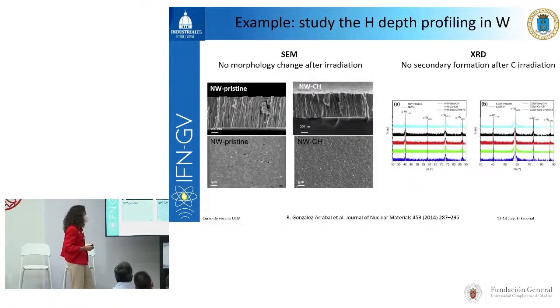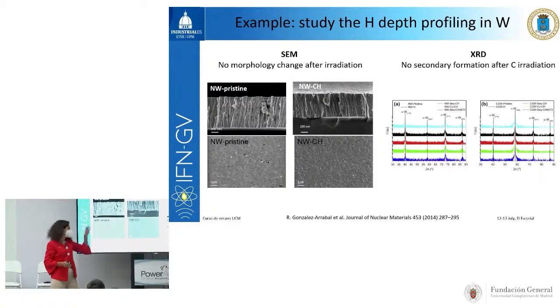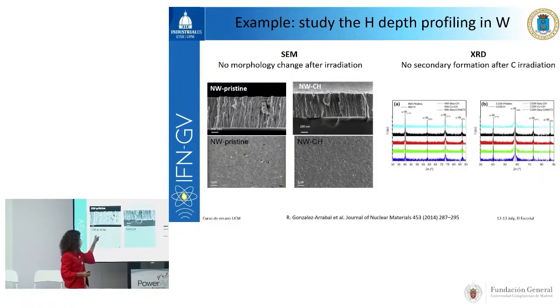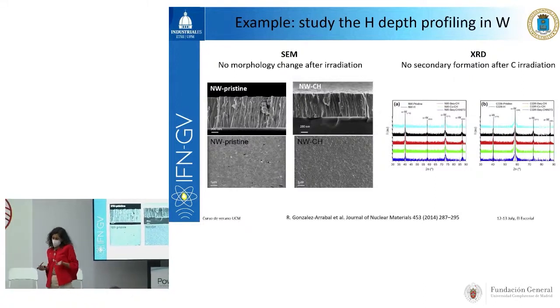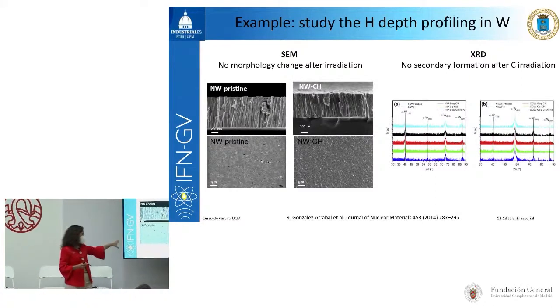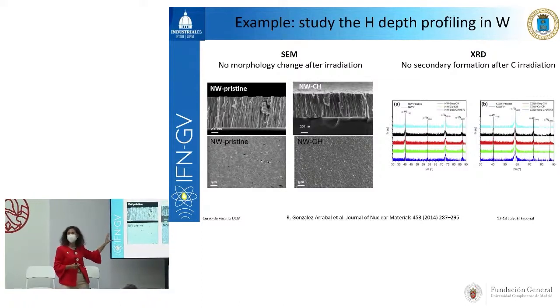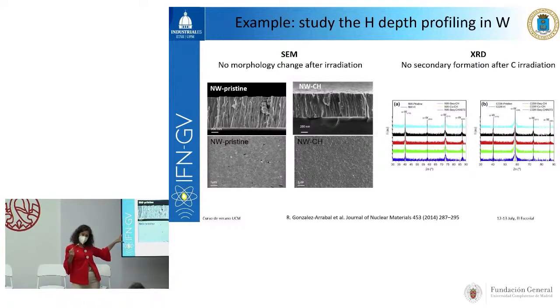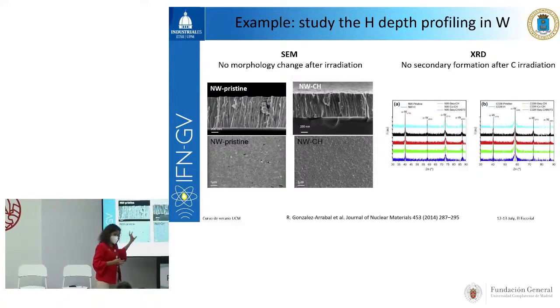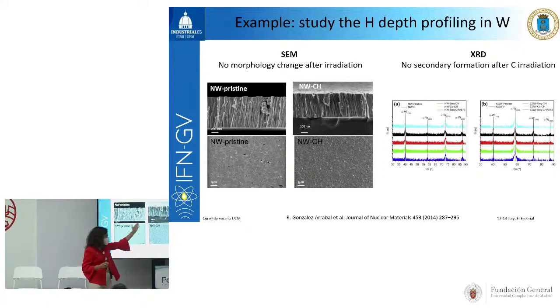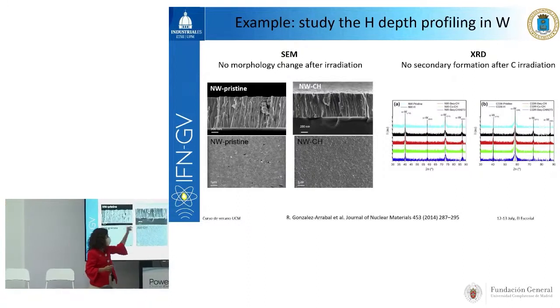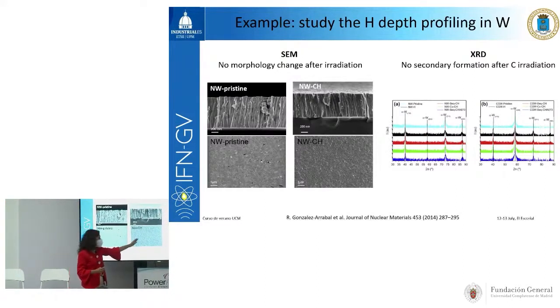We carried out scanning electron microscopy studies. This is the cross-section and the top view of a nanostructure sample, before and after irradiation. We were taking special care in dealing with nanostructured materials because nanostructured materials are metastable materials. So the first thing we need to know is that the material is not modified because of irradiation, that we have exactly the same material, the same morphology, prior to and after irradiation. And here we have exactly the same material. There is no difference between the material before and after irradiation.